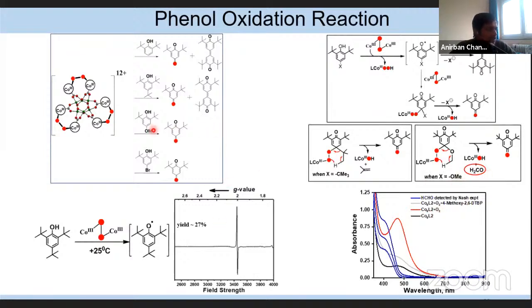So from the product analysis, from the EPR signal, and from the detection of formaldehyde, I predict that this mechanism is quite valid for this phenol oxidation by the end-on peroxo species 2.